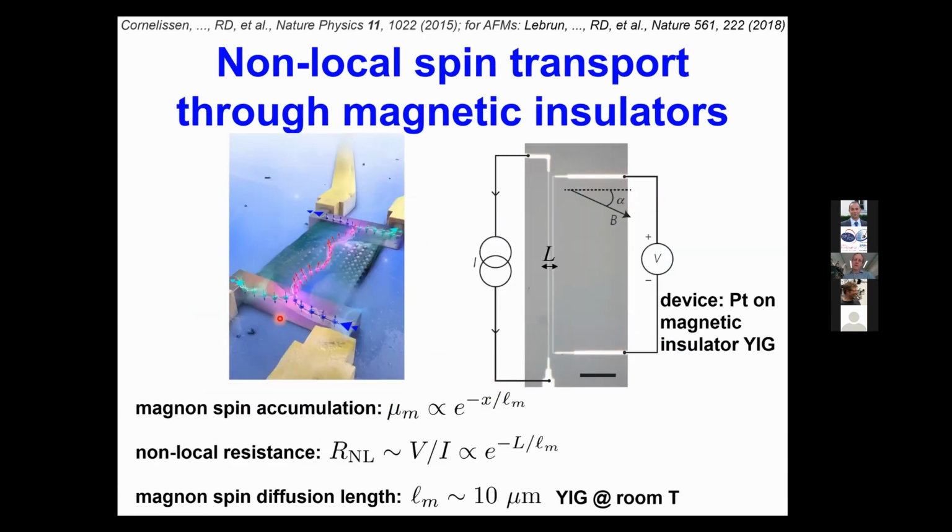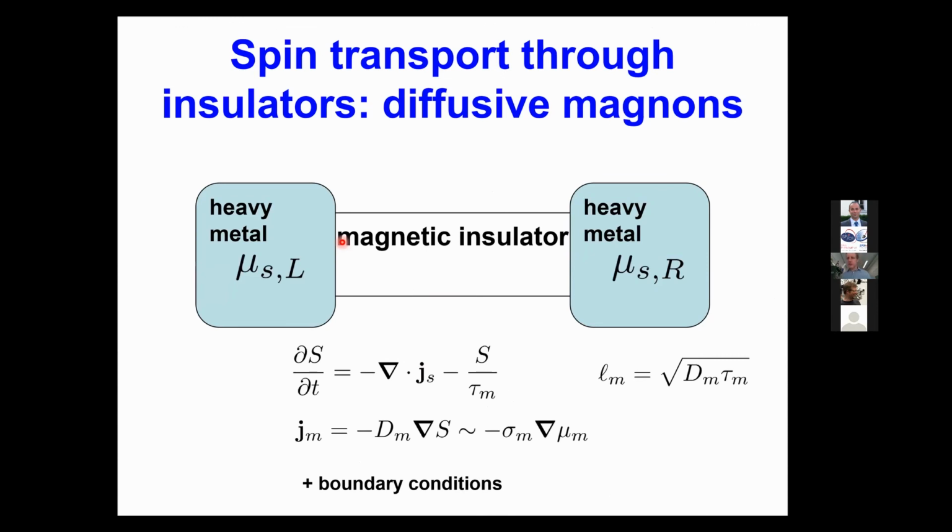So I want to point out one thing, namely that you should really think about this type of spin transport as a biased cloud of magnons that are already there because of thermal fluctuation. So this process doesn't work one by one, meaning that you don't really excite the spin waves that are not there yet. So it's not a process of spin excitation, so to say. It's more like a process of biasing magnons that also happens in linear response even. And actually all these experimental results were in linear response. So that's an important remark because I noticed that there's sometimes confusion in the community about this.